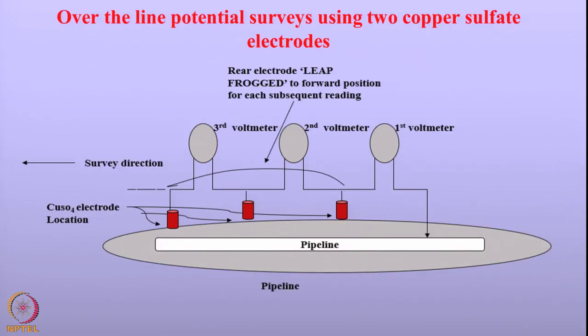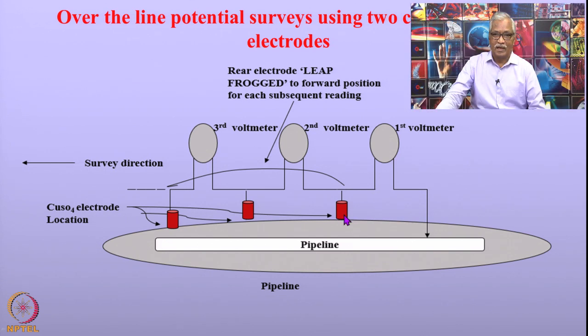So, in order to minimize this, people use two copper sulfate electrodes. The measurement is done as follows. First, you measure the potential of the pipeline at a location. Subsequently, place another reference electrode at a distance, let us say about 1 to 2 meters. Now, the potential difference between these two reference electrodes is measured.